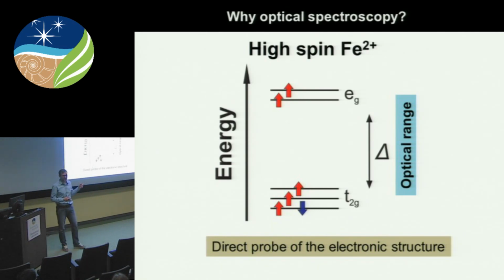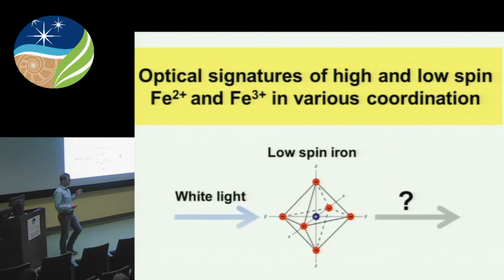The reason optical spectroscopy works well is simply because the energy difference between the T2g and Eg levels usually lies in the optical range, which means that you can shine white light on your sample, and that white light will excite an electron from the T2g level onto the Eg level, and that will give you an absorption band in the spectrum. Then you can use the energy of this absorption band, its spectral position, to say something about the electronic structure of iron in the mineral that you're probing.